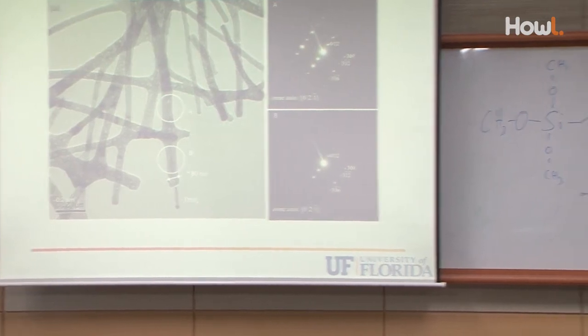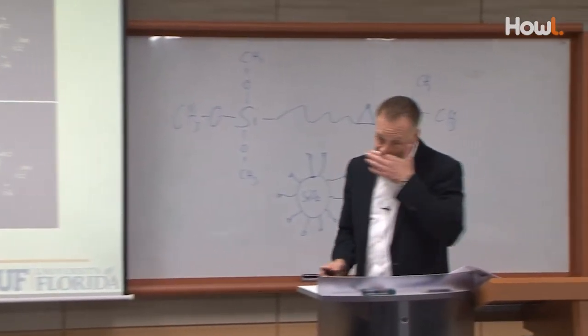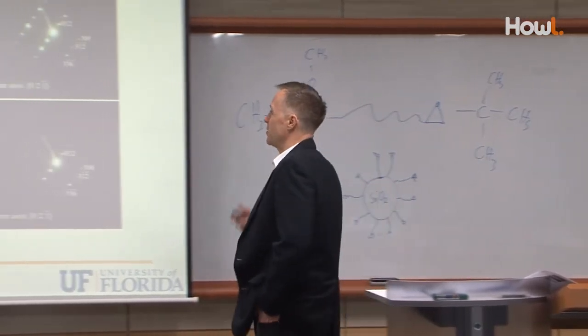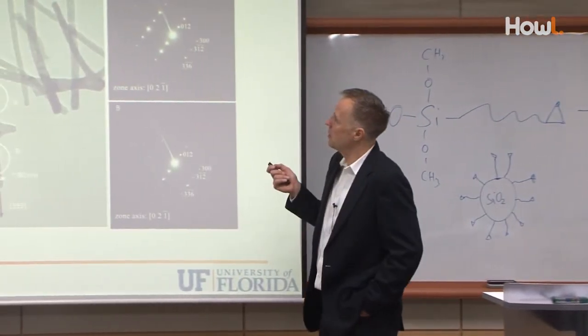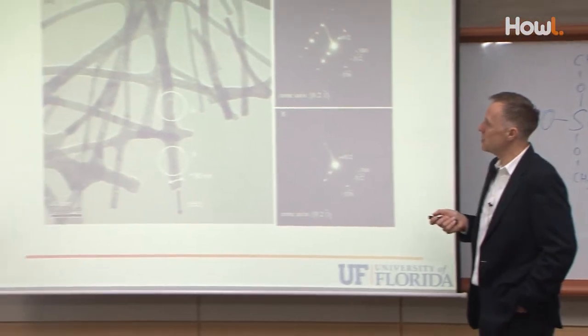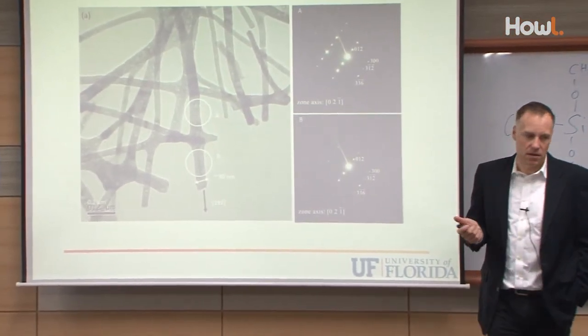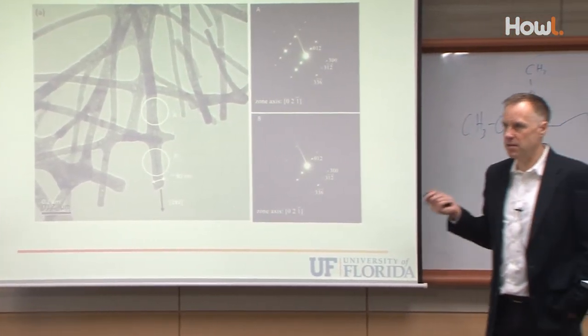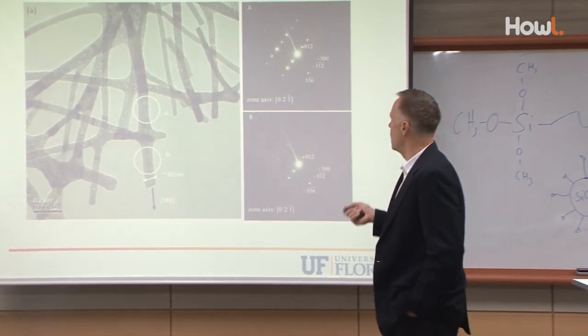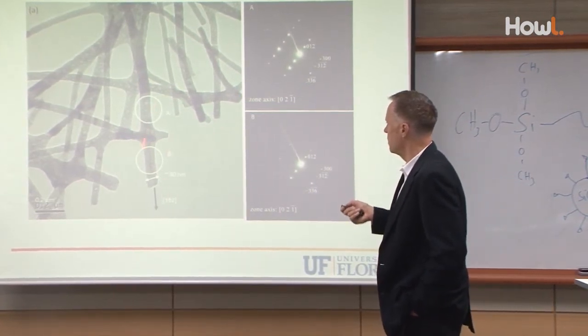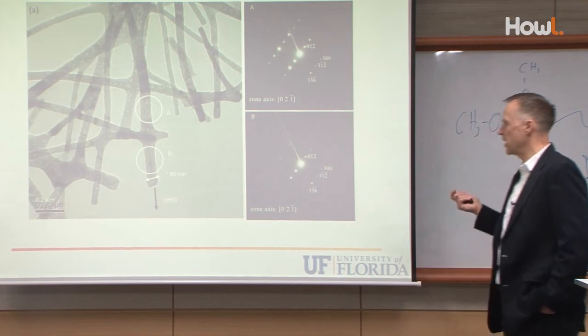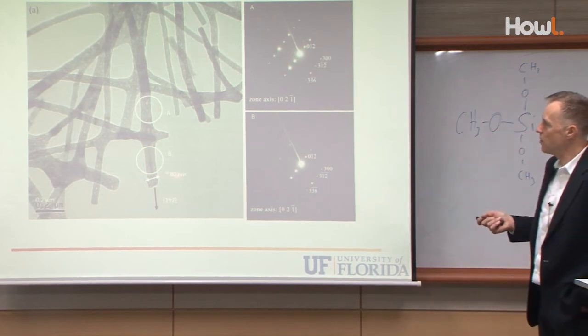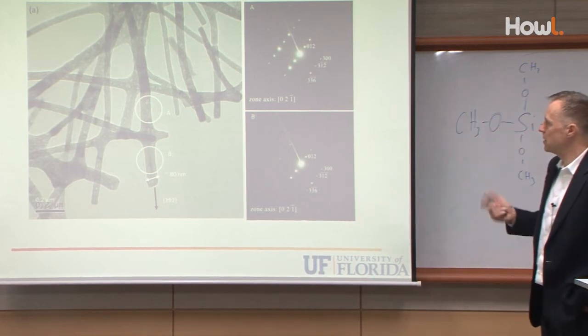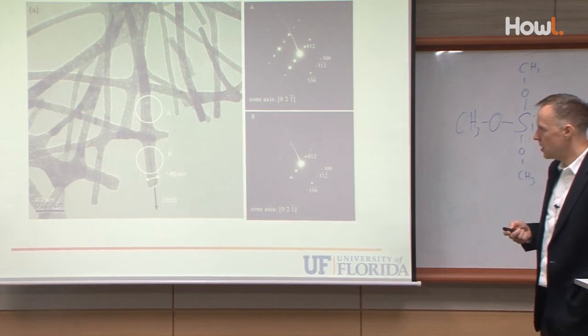Another thing that is possible, you can crystallize these compounds. If you work, for example, with alumina precursors, and tin oxide, many others have been shown, you can turn them into single crystal fibers. This is coming also from the heating profile and the dimensions of these objects. And when you do selected area electron diffraction in the TEM of such structures, you find that we're capable of making single crystals.